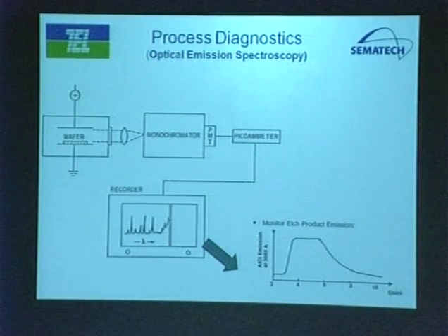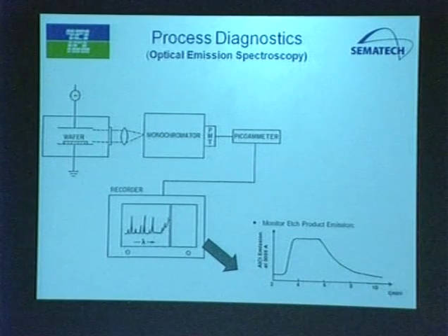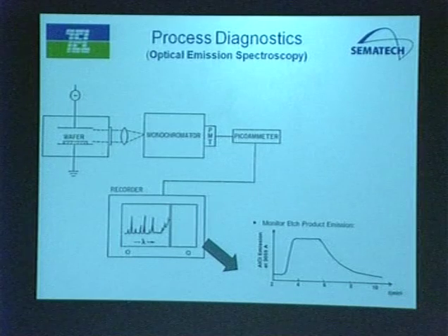So in fact, what we do is we look at the signal. Now I see the film starts etching here, so the signal goes up. Flat, so keep on etching. The film is etched, so the signal drops down. We call it the endpoint, about here. If we monitor this, each wafer will be processed the same way, because the chamber changes and the wafer sometimes changes a little bit. So endpoint makes sure that your etching is very precise. You don't want to under etch, so the film is not etched completely, and you don't want to over etch, so the underlying layer is damaged. That's where OES comes in. This is widely used in the industry. Everybody uses it, and it's all automated. We do some manual, but mostly it's automated.